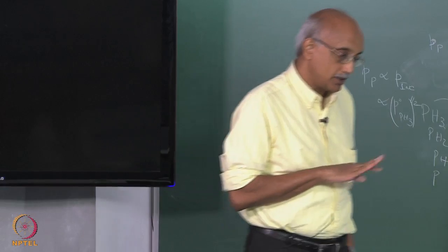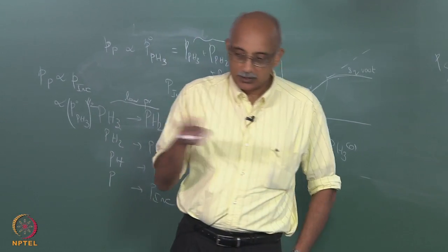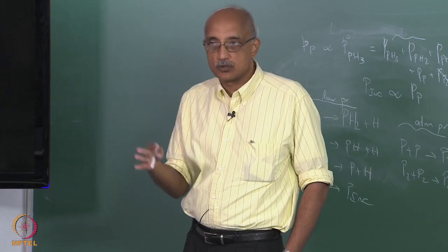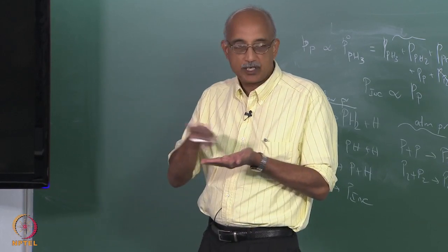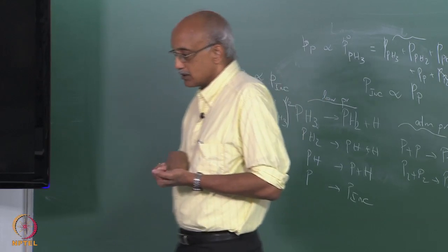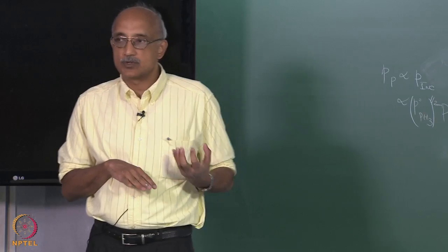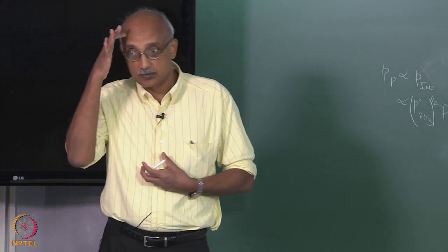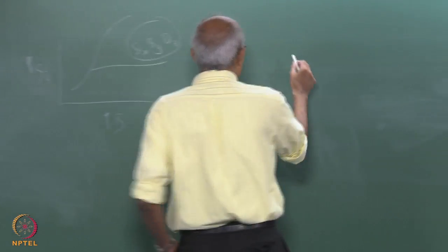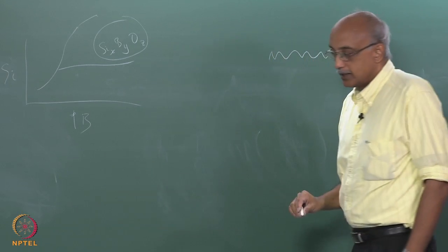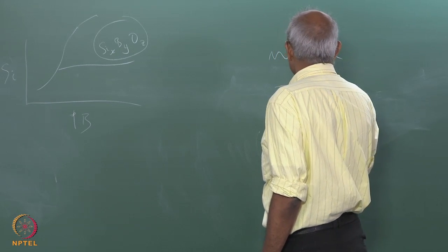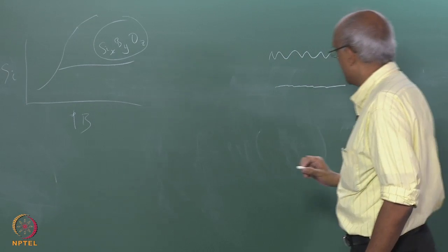And that is important to capture because the surface characteristic of a CVD film also has an influence on the sticking coefficient. In other words, as the CVD film becomes smoother and smoother, its capture efficiency or sticking coefficient for arriving molecules will change. And the change is not always positive or negative. For example, if you have a glass surface that looks like this, and let's say that by putting in some additives and flowing it at high temperature, you have been able to make it look much smoother on a microscopic scale.